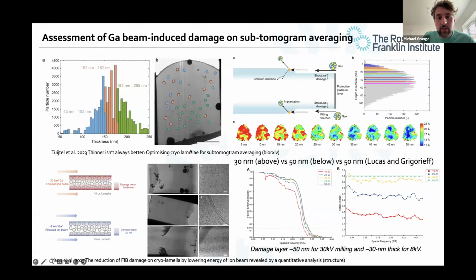But we still don't really fully understand that process. Just important to put this into context, there's quite a bit of work out there since we published some of the original damage studies which show gallium ion beam damage, and this is just a few examples. So there's Martin Beck's lab, there's some work which I think just recently came out as a fully published article, and they show that there's damage up to 30 nanometers, and then you get usable particles beyond that, or at least better particles.